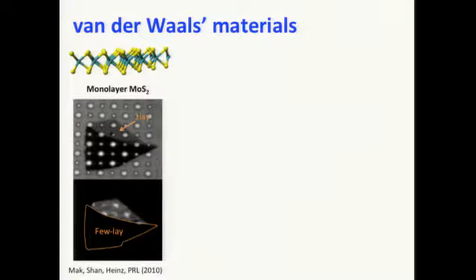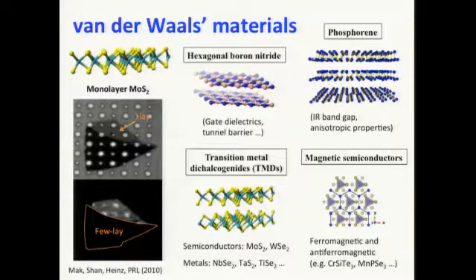This material has a very similar structure compared to graphene, which is also a layered structure. And it turns out that when you thin down the material to the monolayer case, there's quite a dramatic change in the electronic structure. The material turns from an indirect gap semiconductor into a direct gap semiconductor, which is best illustrated in this picture here. This is the optical image of a few-layer MoS2 versus a monolayer MoS2. Here is a photoluminescence image showing that only the monolayer becomes bright in photoluminescence, illustrating the dramatic transition of the band structure. Ever since then, MoS2 is only one example.